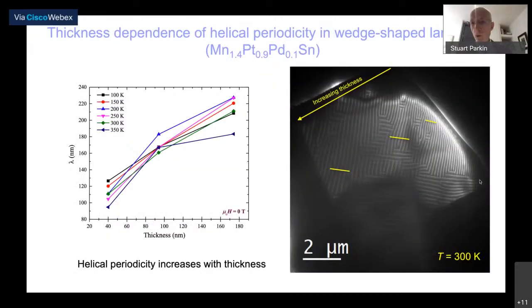Now, what we discovered was, from this Lorentz microscopy, we could look at how the period of these helical structures, again, these are shown here, changes as we increase the thickness. And you can even see in this Lorentz micrograph on the right-hand side by these yellow lines, as we increase the thickness of this lamella, you can easily see that on the right-hand side, the period between the white and black lines is much smaller than on the left side in the thicker region.